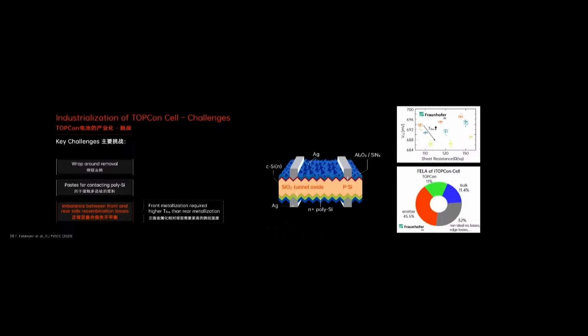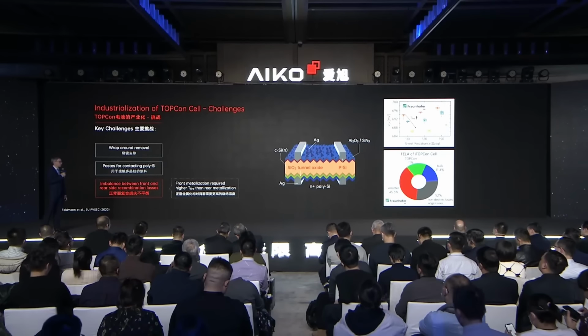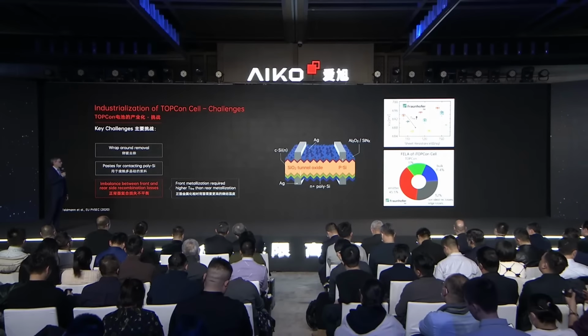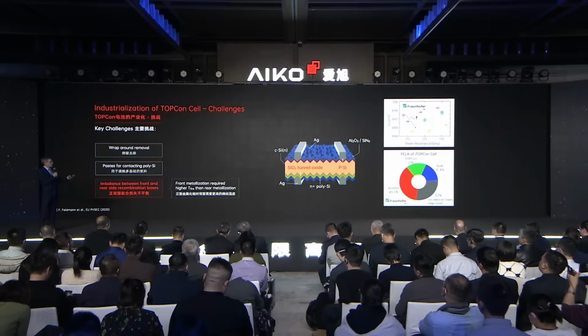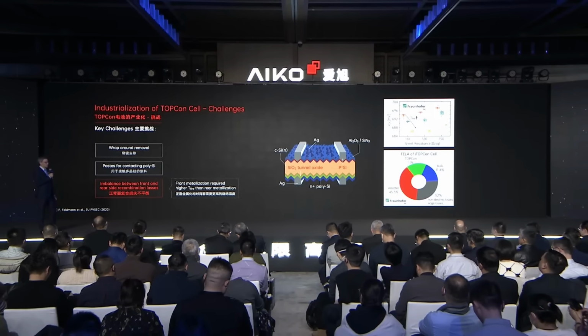Then another challenge was that there was an imbalance between front side and rear side recombination, and that was mostly due to also non-optimized contact formation, especially at the front side. So at the front side we have silver aluminum paste, which typically needed higher firing temperatures than the rear side paste, and we saw at Fraunhofer that we need a higher temperature to get a good fill factor, but then, as you can see on the graph on the upper side, higher firing temperatures also led to a decrease in the VOC, so there was quite a trade-off, and such cells were strongly limited by recombination at the front